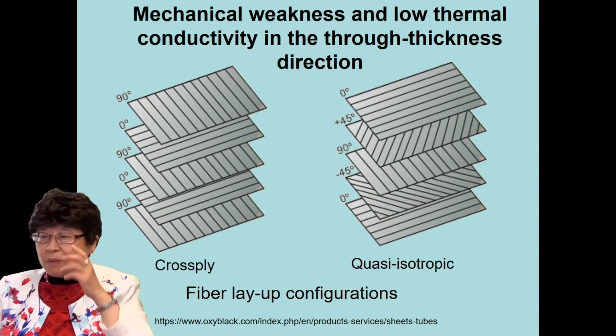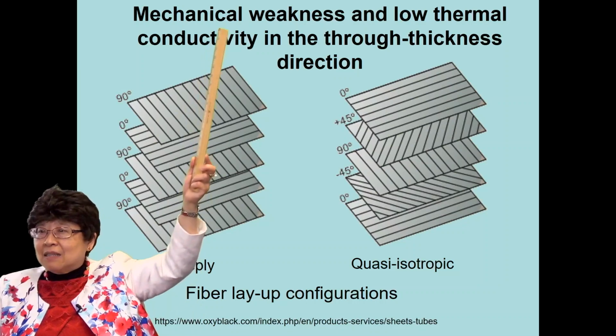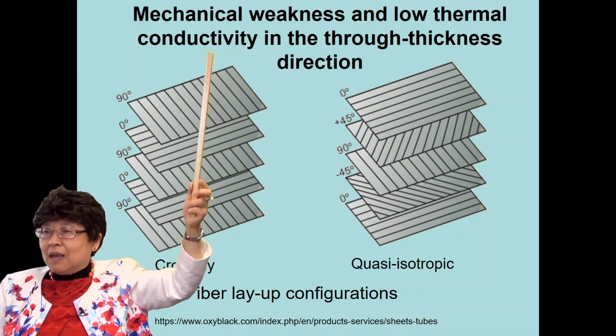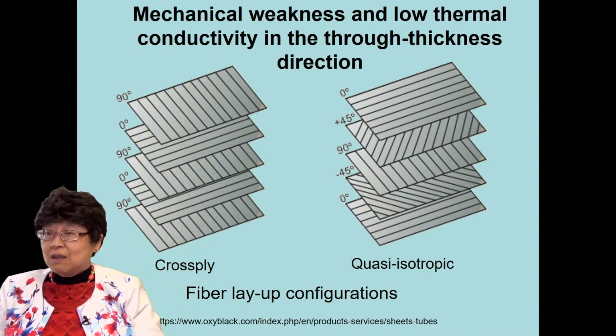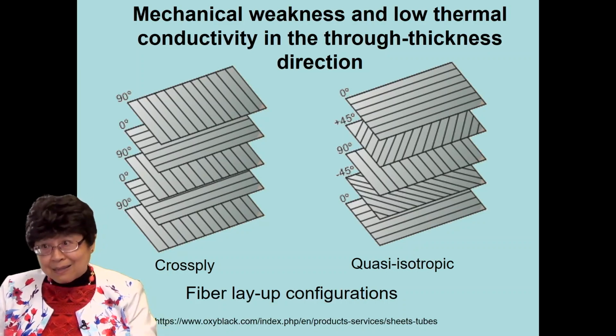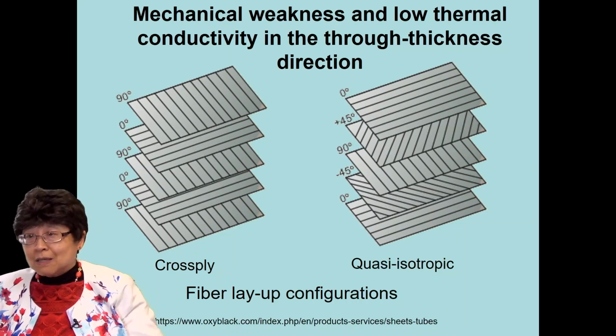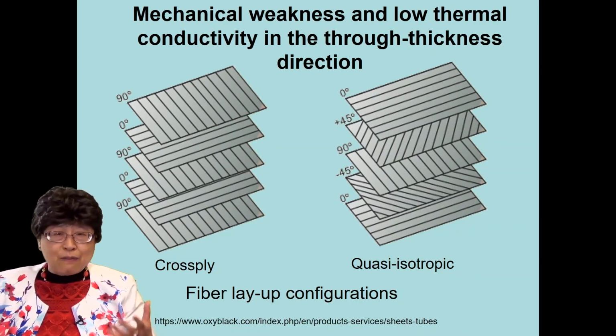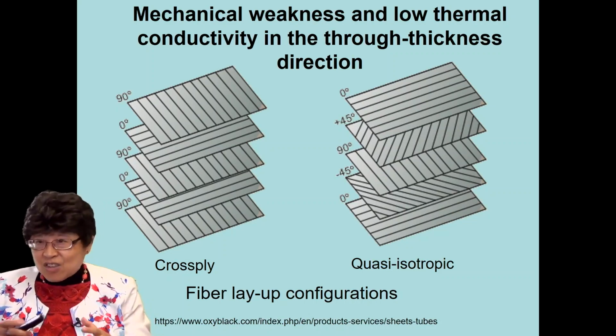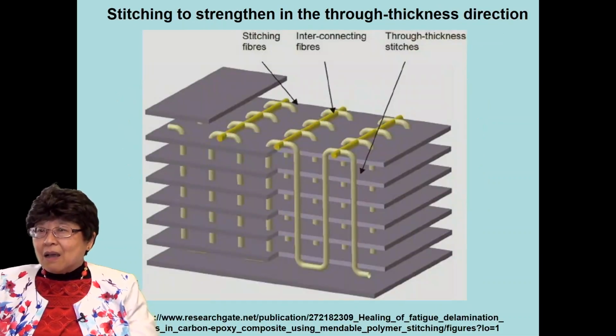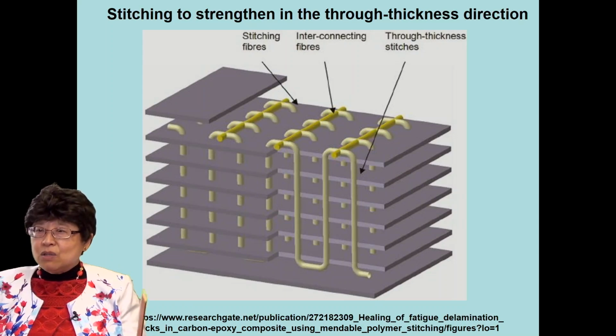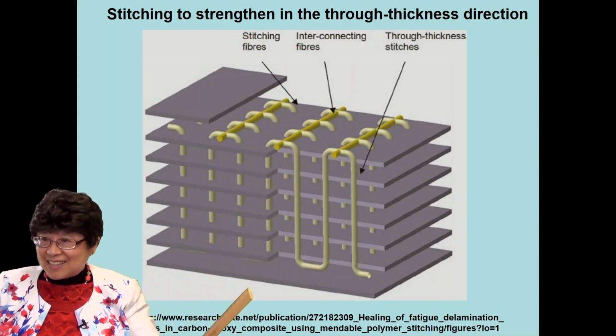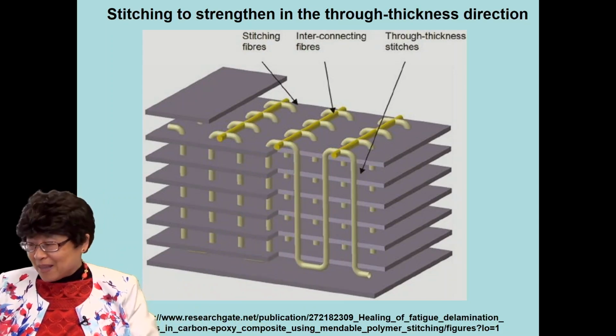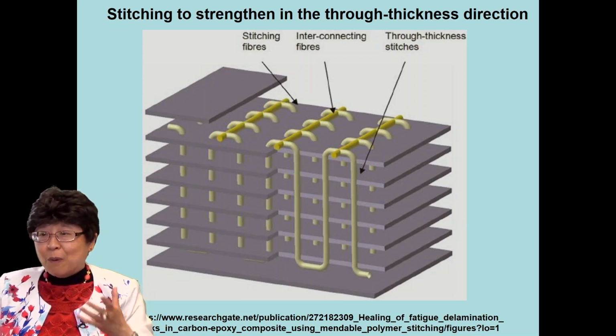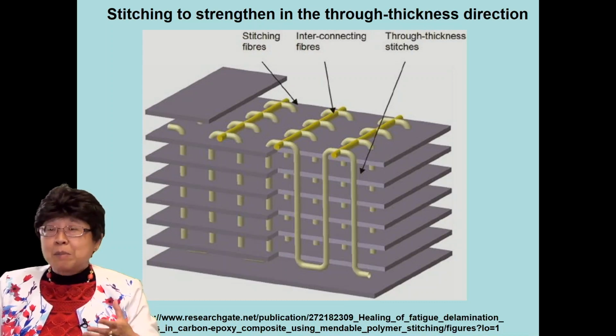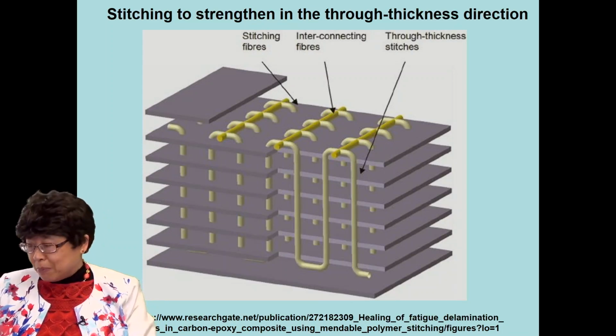Okay. However, this layup situation has one problem, which is it's mechanically weak and low in thermal conductivity in the through thickness direction, in the through thickness perpendicular direction. No fibers in that direction. So it's mechanically bad, and the thermal conductivity is low. Now, the thermal conductivity turns out to be very important for aircraft, because the aircraft, particularly the engine part of the aircraft, gets hot, and you need to get the heat out. One way to alleviate that problem is to do sewing again, stitching. Yeah, this yellow thread. Okay. In the fiber preform, before you put in the polymer matrix, so it's still easy to sew, then at that point you do the sewing. Okay.